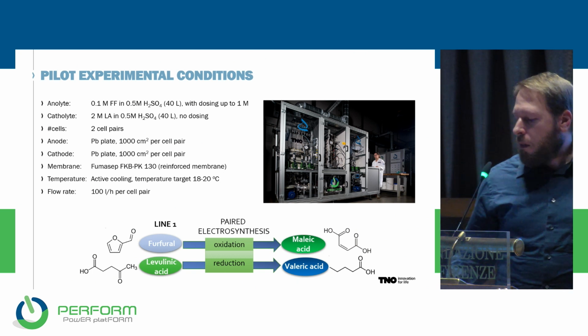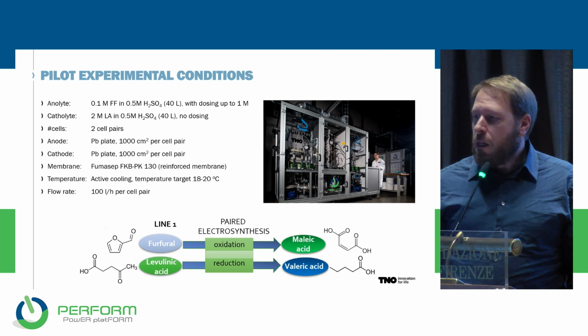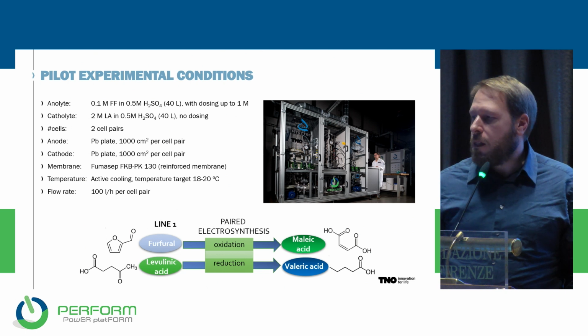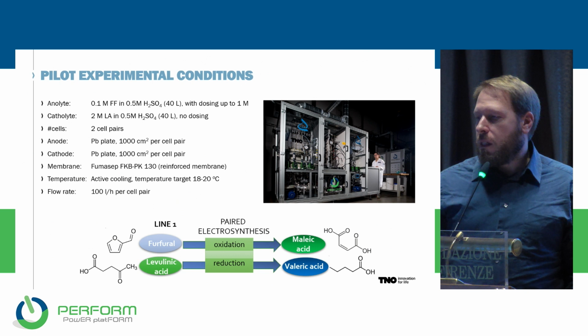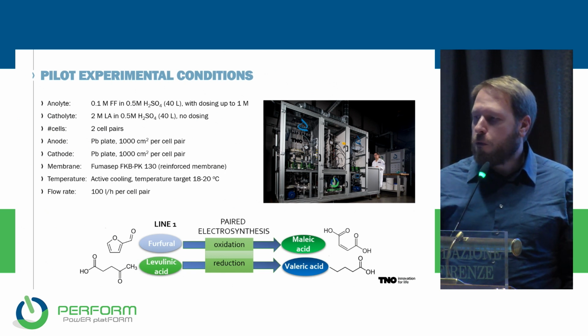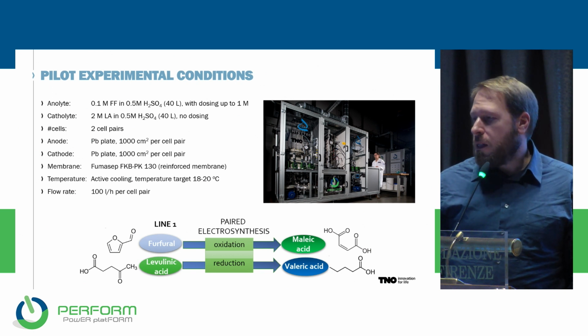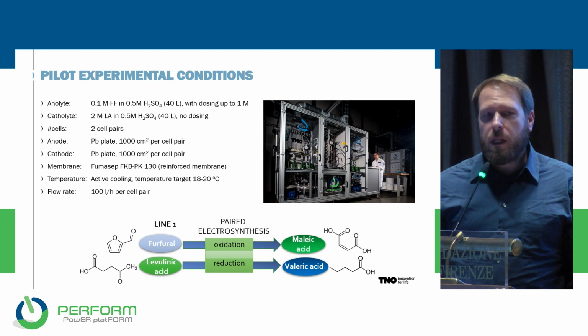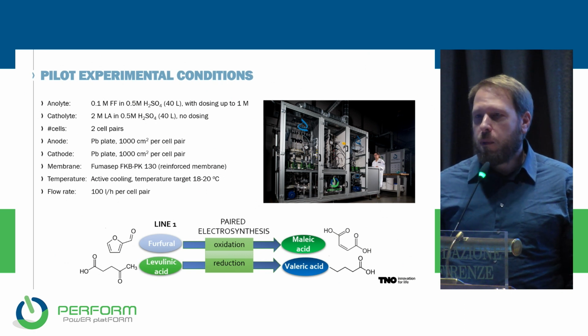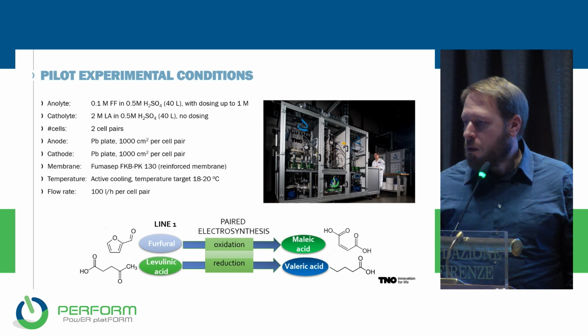Now I will focus on one single experiment that we did. These are typical conditions for our experiments. We have done this sort of experiments more than once, on different conditions but also different cell pairs. Because we want to run this in a paired system, we have furfural on the anolyte side and levulinic acid on the other side. For furfural, we try to keep the concentration low, so we start with 0.1 molar and keep dosing furfural throughout the reaction. For levulinic acid, we decided to use a 2 molar concentration and do no dosing. In this case, it was only 2 cell pairs with 1,000 square centimeter per cell pair with a Fumasep membrane, and we also try to keep the temperature constant, which is a bit of a challenging part.